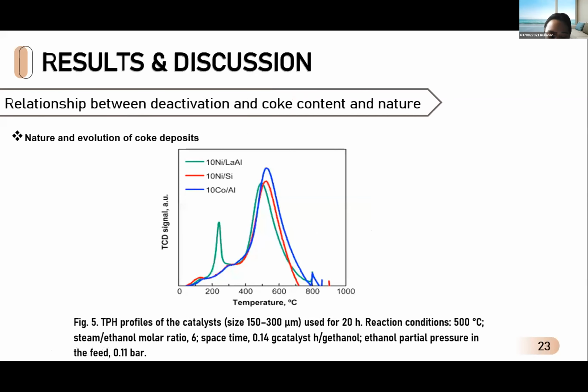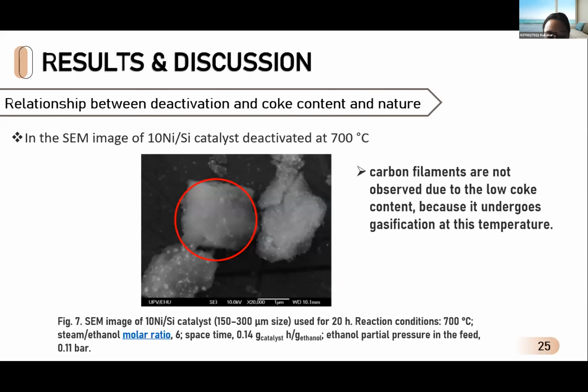Figure 5 shows the major peak at 500 to 530 degrees Celsius, corresponding to the hydrogenation of carbon filaments, and another major peak at 300 to 350 degrees Celsius, corresponding to another fraction of polymeric and non-structured coke. And in figure 7, carbon filaments are not observed due to low coke content because it undergoes gasification at that temperature.